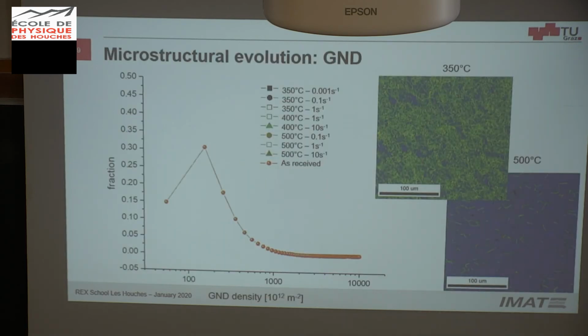We were also trying to quantify geometrically necessary dislocations. This is what you get from the CAM maps, and this is the evolution for the as-received condition. Of course, the as-received condition is also a mixture of dynamically recovered and statically recrystallized structure. And by deforming at low temperatures, we increment the stored energy.